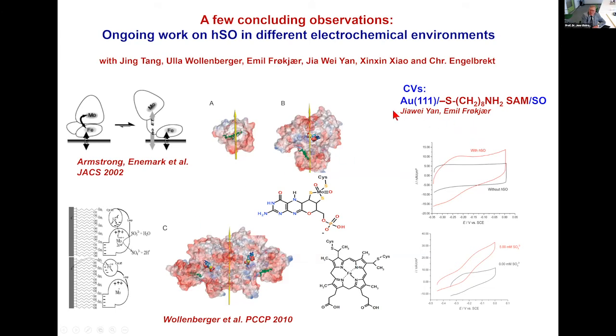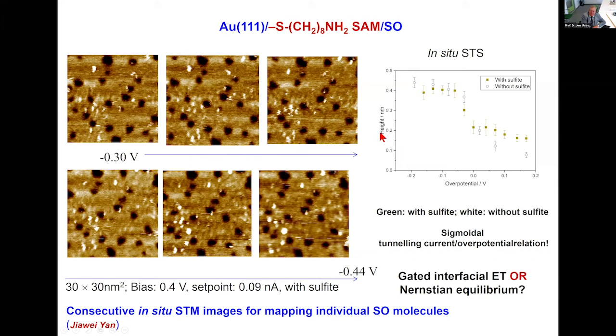Now, from Emil's work and that of Jiawei Yan, who was a visiting professor in the group, we could measure the voltammograms first without enzyme: no electrochemistry except for capacitive. With enzyme, there is a voltammogram. And it is quite notable that there is apparently electron transfer also for the enzyme without the substrate sulfite. But with the sulfite substrate, you can see there is a much stronger signal, a nice looking electrocatalytic voltammogram. Also here we have scanning tunneling microscopy, and here is a tunneling spectrum which has this sort of sigmoidal shape that we have seen before also.